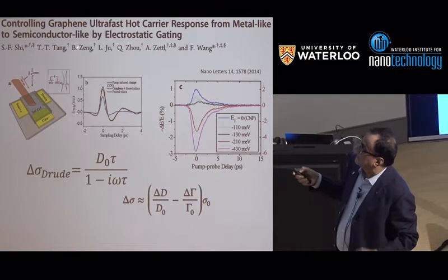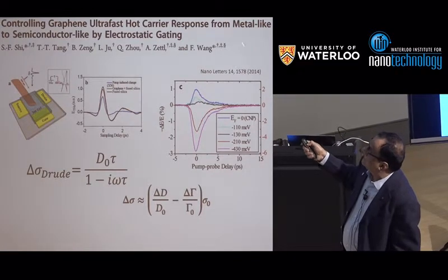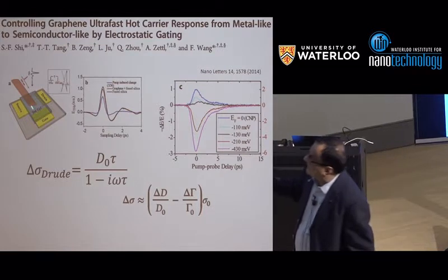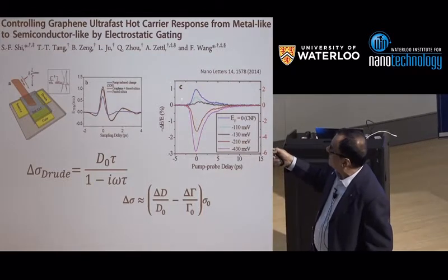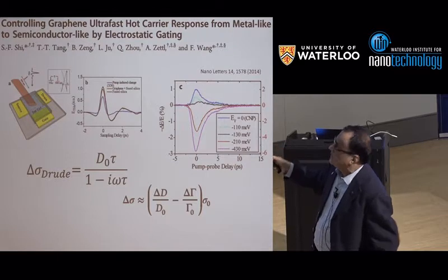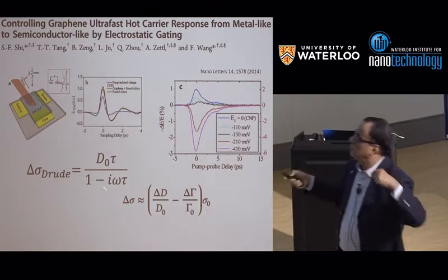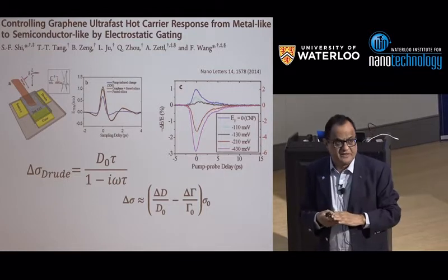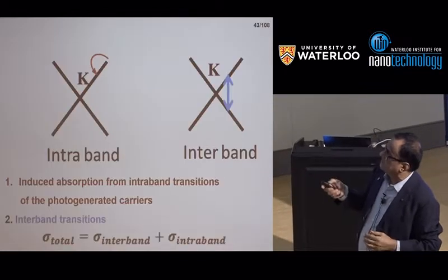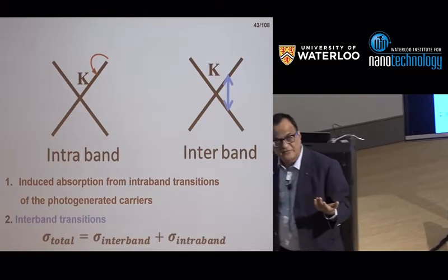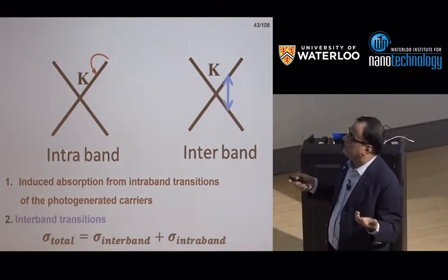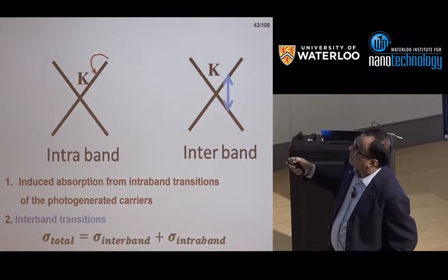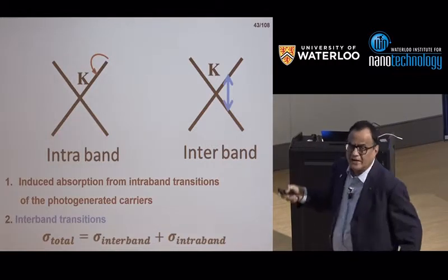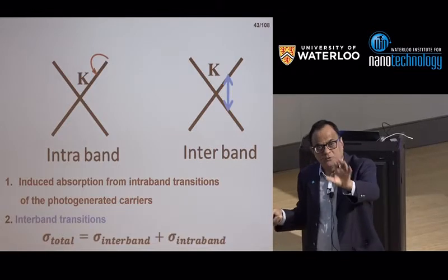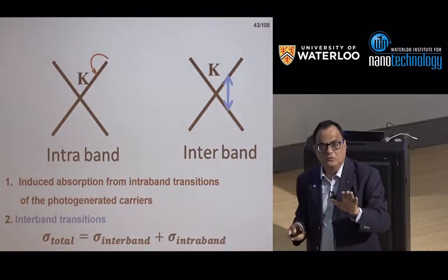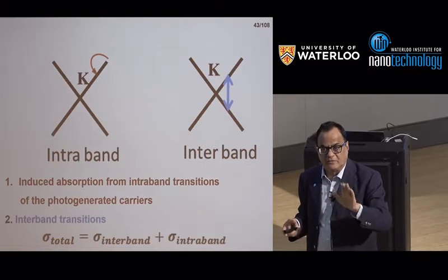So then at the same time, another group did these experiments using electrostatic gating and showed on the same sample by varying the doping, you can go from negative to positive photoconductivity. Now, this is something I will give you a quick understanding of because it's quite informative. With terahertz, we are looking at intraband processes and the terahertz is getting absorbed by those carriers. Now, this will always give you conductivity which is positive on pumping.